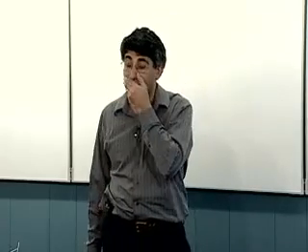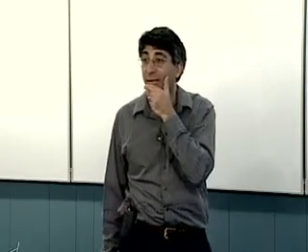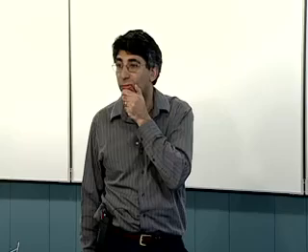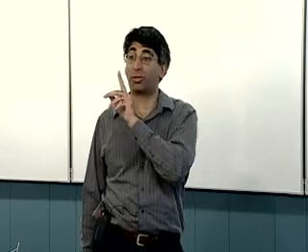Yes? Maybe I missed the CV part, but if you have a virtual diffusion, why the CV? Right. So the CV doesn't show the diffusion. Why? So the issue is an issue of time scales. Okay. The CV goes slow enough that you are always charge transfer limited. You never pump enough electrons out there that you have to wait for the self-exchange to occur.